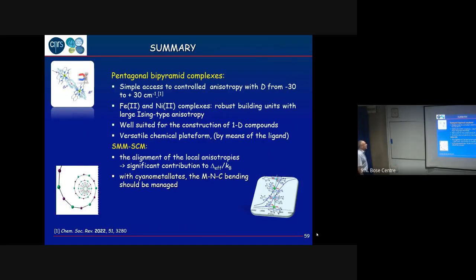So this is the summary of what I was telling today, or let's say a summary of the important things I would like to stress. With these pentagonal bipyramid complexes, you have very simple access to a controlled anisotropy, with D values that can go from -30 to +30. This depends on the metal ions you are going to use. With iron(II) and nickel(II), we have large Ising-type anisotropy. This is really useful for trying to make the compounds we are interested in, that is, single molecule or single chain magnets.